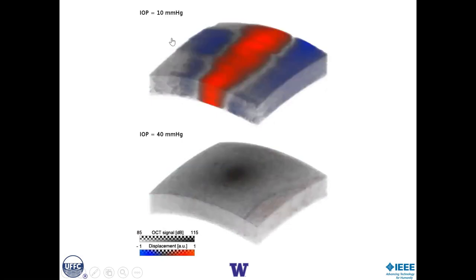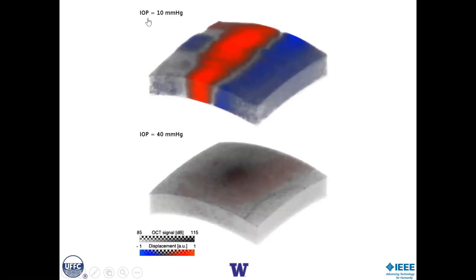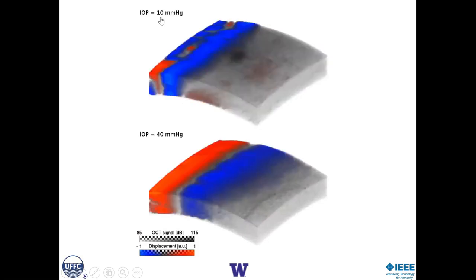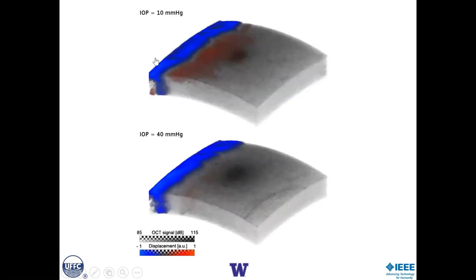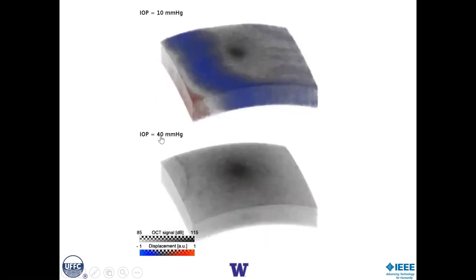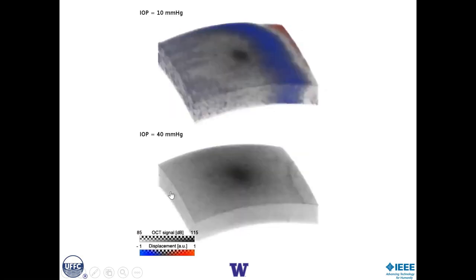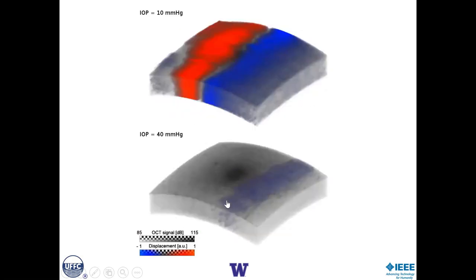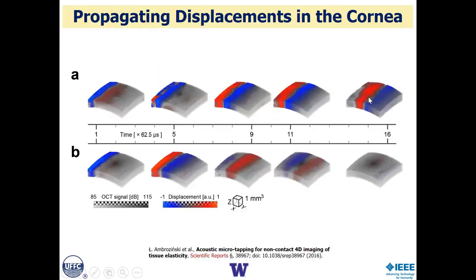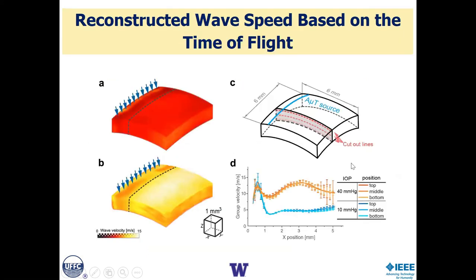And we're comparing in a pig model the wave propagation when we hold that pig at 10 millimeters of mercury as the intraocular pressure, which is a normal pressure, versus a highly elevated pressure of 40 millimeters of mercury here. And as you can see, the waves travel much faster in the higher pressure system. We can track these fields. So we have these wave fields in 4D, so in all three dimensions, with all voxels within this three-dimensional grid, as well as all time points over the experiment. We can then reconstruct the wave speed, and compare it between the two intraocular pressures.